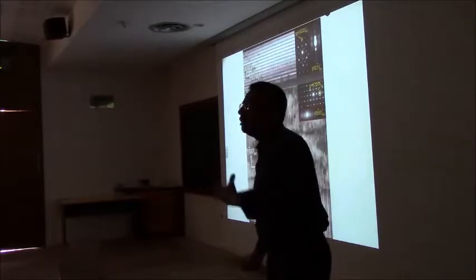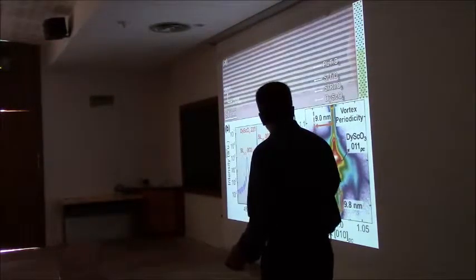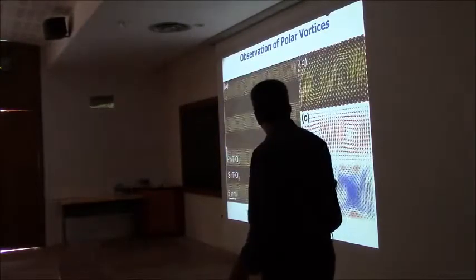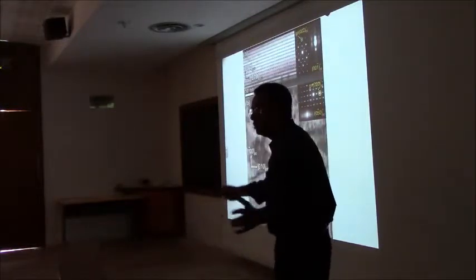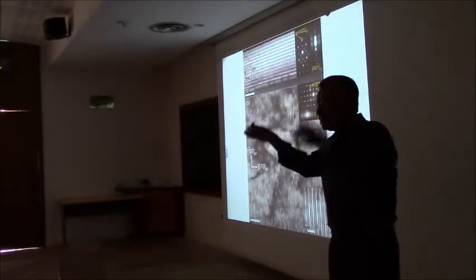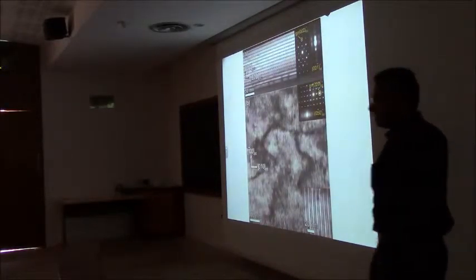And again, you could say, oh, look, you changed your mechanical boundary conditions. How do you know this is representative of the sample? One way to look is this guy. And this is why I was making such a big deal out of it. These guys are essentially the same as this spacing. It's picking up those. So you could see that there are regions which are oscillating, high intensity, low intensity. We're going to get back to it in a second. That spacing is about 10 nanometers. That's approximately the vortex, anti-vortex, vortex spacing. Okay. So from the top, it looks very different.